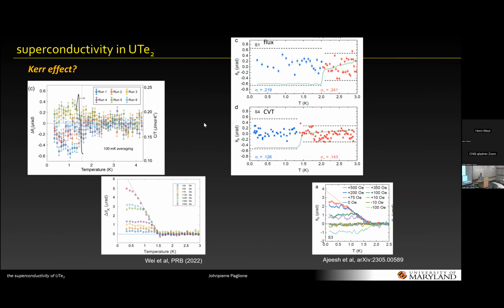So some more recent work has emerged that suggests that may not be true, or there's some complication. So first of all, the Kerr effect was measured also by the Los Alamos group, Sean Thomas. And they're claiming not to see a Kerr effect in these zero field cooled measurements. And there's some debate between these groups, which ironically, Sean was an academic grandson of Aaron's. So the data is fairly similar, except the Los Alamos data suggests that there's no change through TC of the Kerr effect. Is it a different sample or is it the same sample?